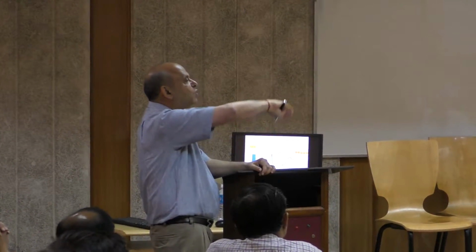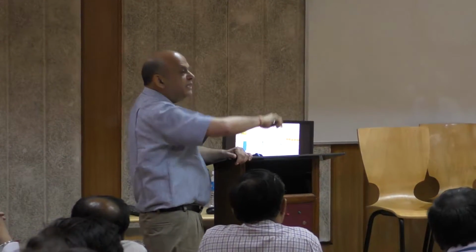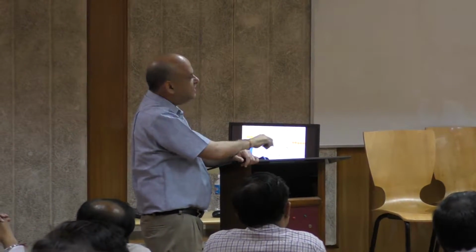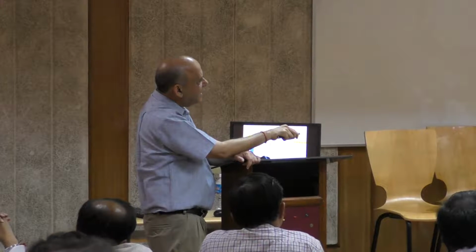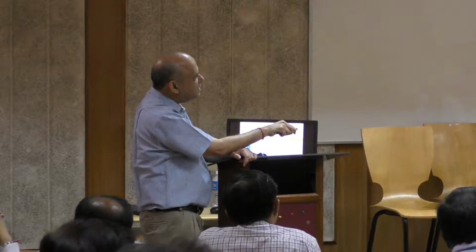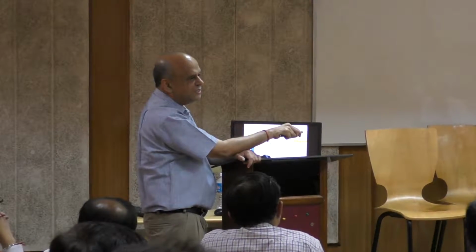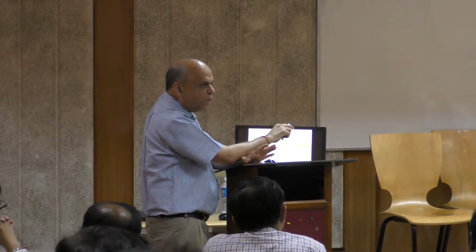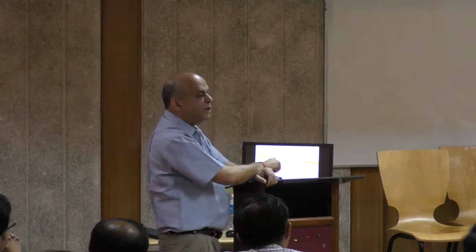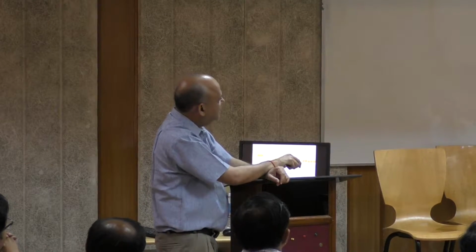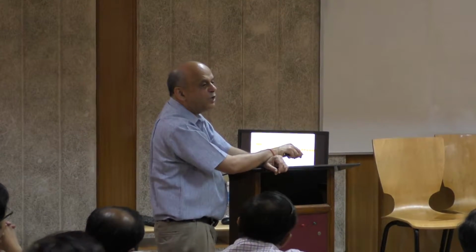The response is not now DC. It is just an increase in the resistance and then a decrease in the resistance. When you remove hydrogen gas, again there is an increase in the resistance and there is a decrease in the resistance. This complete modification of the mechanism has taken place when we have gone from palladium bulk, palladium wire or thin film to palladium nanoparticle. And we now understand because there are two processes which are taking place. We call them a geometrical and electronic effect.